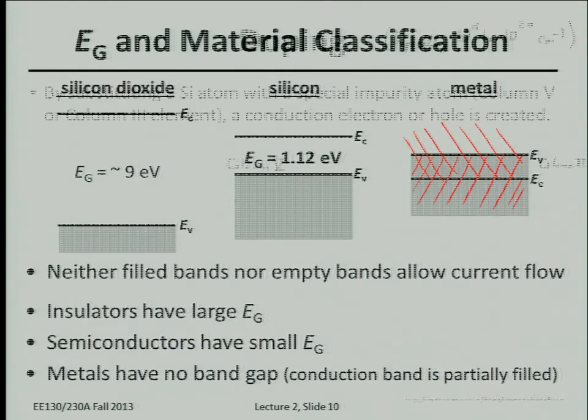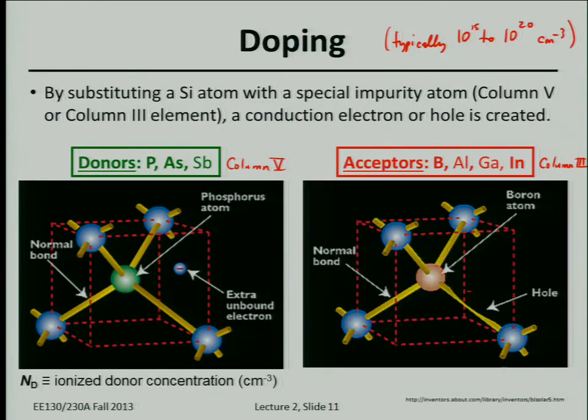And when you fabricate a semiconductor device, this is one reason why you shoot donors into the silicon. You have to heat it up to like 1,000 degrees just to get the atoms to rearrange and bond like this. But this donor is bound to the silicon, and it's not going to be moving around. It'll vibrate about its equilibrium position, but it's not going to physically move around and conduct current in your semiconductor.